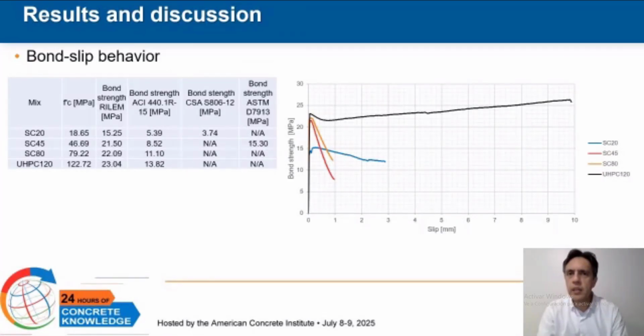For example, in UHPC, RILEM testing measured 23.04 megapascals, while ACI predicted only 13.82 megapascals. This underestimation is consistent across all mixtures and highlights the limitations of existing standards when applied to high-performance concretes or when bond is mobilized under flexural stress states.